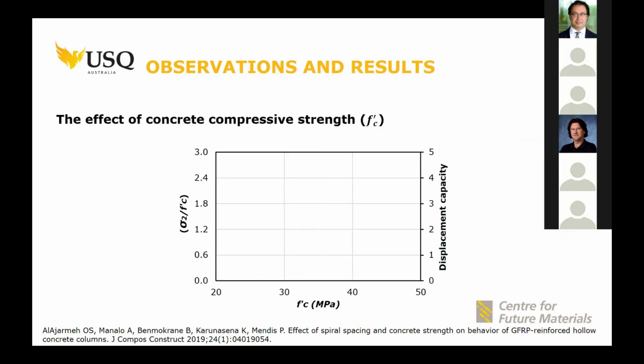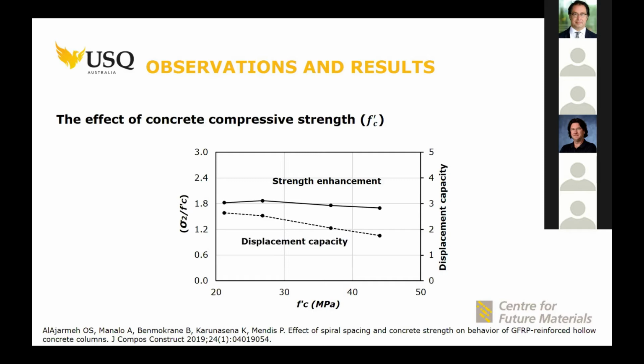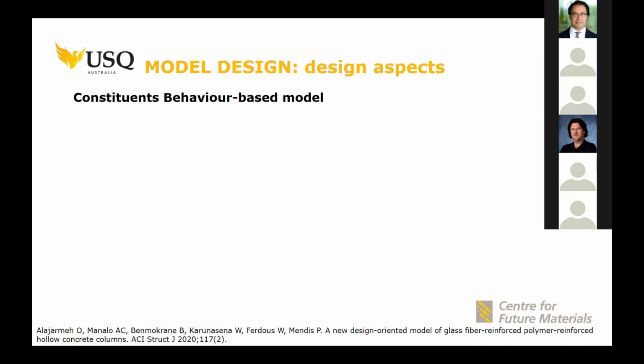For the effect of concrete strength, no strength enhancement was observed on the concrete columns with GFRP bars, because the number is normalized, and the normalization for all types of concrete gives us the same strength enhancement. However, the displacement capacity is reduced with the increase of concrete strength, because the brittleness of the concrete increases with the increase of concrete strength.